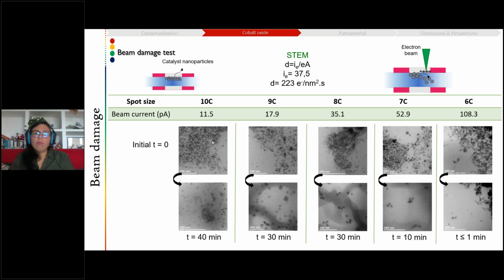If we use a very low electron dose, a very low beam current, the particle will remain longer on the observation window, but of course, the resolution will be worse. And if we use very high doses, we will see the particles better, but they will stay only very short times. So we decided to use an electron dose that gives us enough time to see our particles without degrading them or making them go away. This is for this particular case, but in other cases your beam can induce changes in the materials you are observing, so it is very important that you evaluate this electron beam effect.